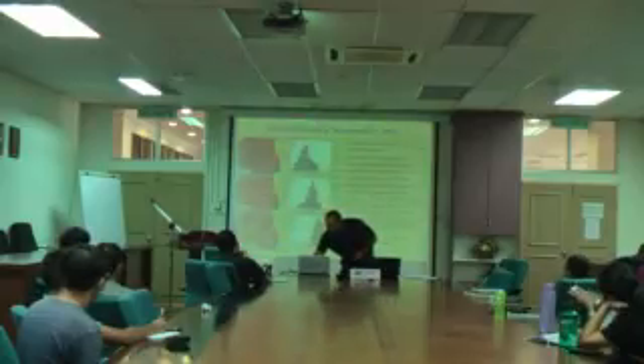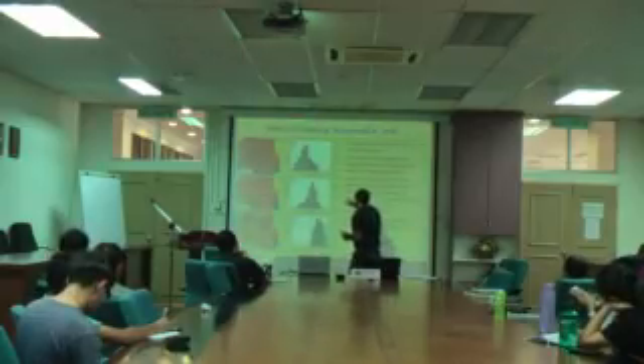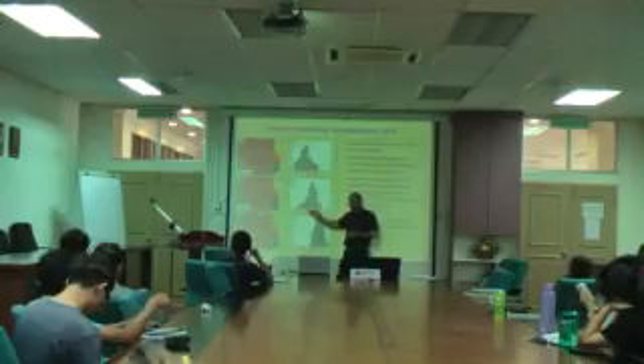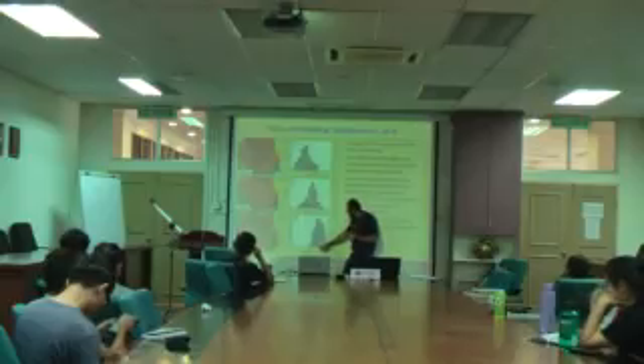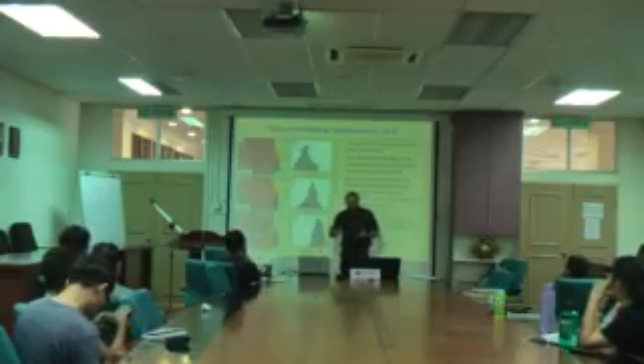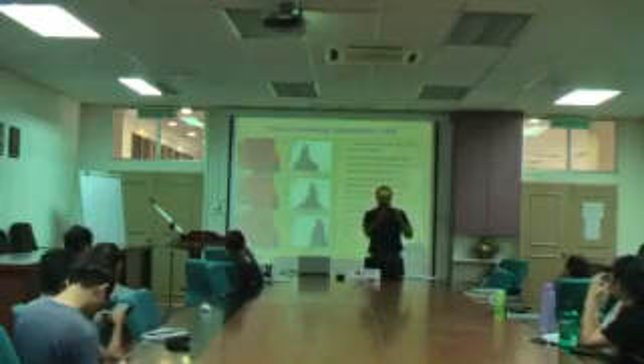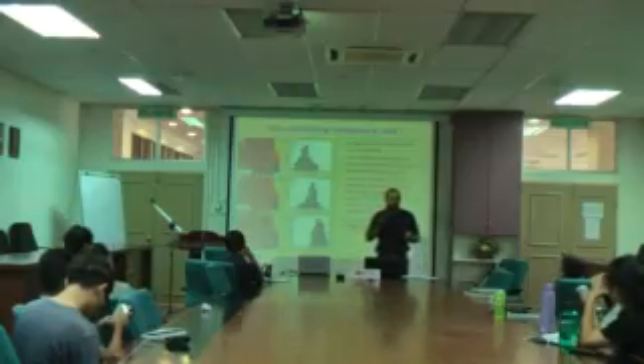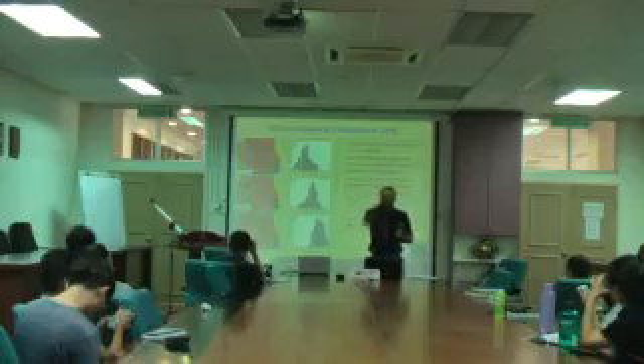So if you remember our size, let me go back to this one. This is how much? Around 31. This is okay. We can see not strong, but we can see quantum confinement. This one is 40, almost 2 times more than the exciton Bohr radius of germanium. This one is around 50 something. But you know, confinement effect always happens in 3 dimensions. This is okay, our width is around 40. But our height is around 4 to 10 nanometers. So in the y direction, in the height direction, we can see the confinement.